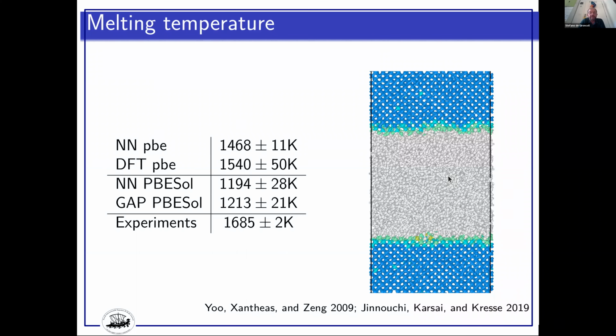An alternative functional that has been proposed and actually advertised as more accurate for solids is PBEsol. And we found, actually, we originally started with PBEsol because we thought it was better, but instead it is much worse. The melting temperature is only about 1200 Kelvin, and this is indeed what GAP potentials also obtain.